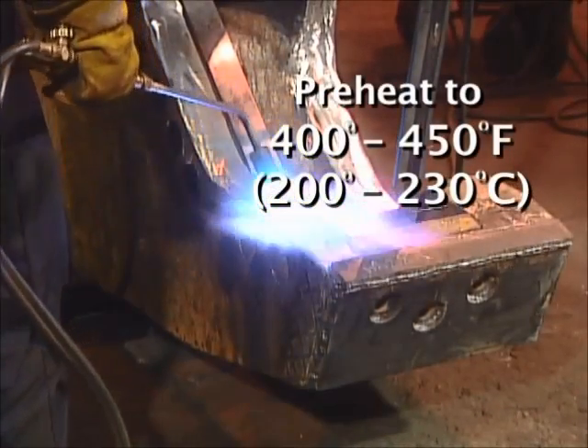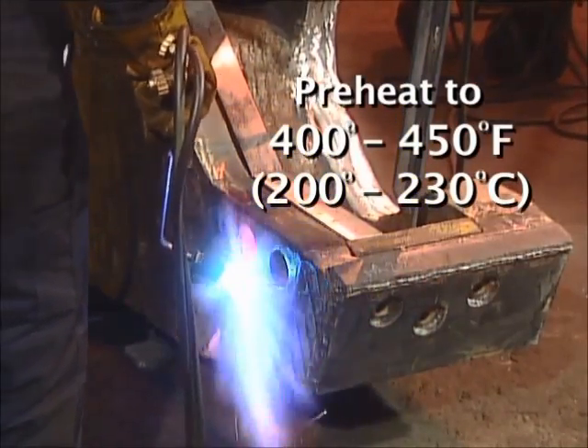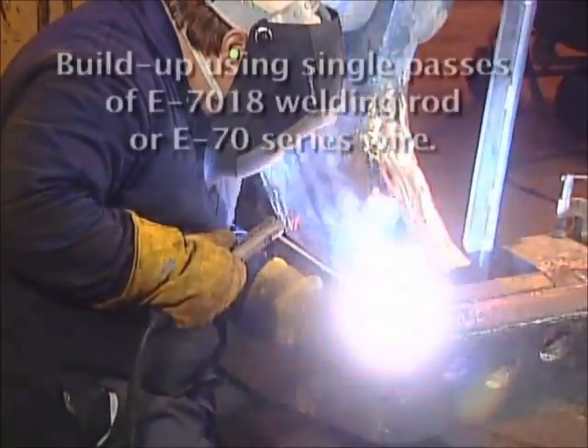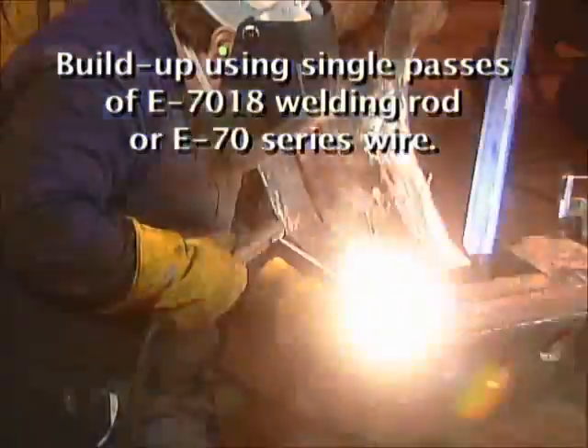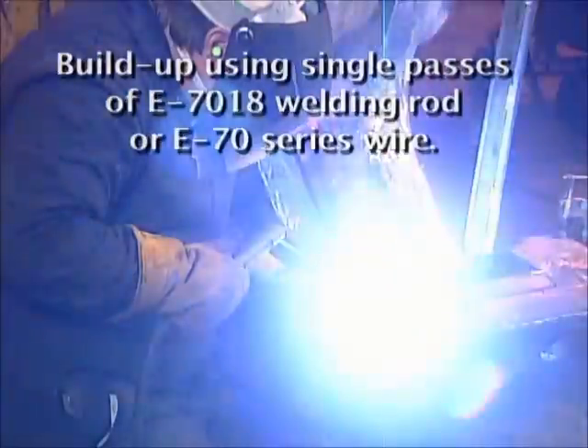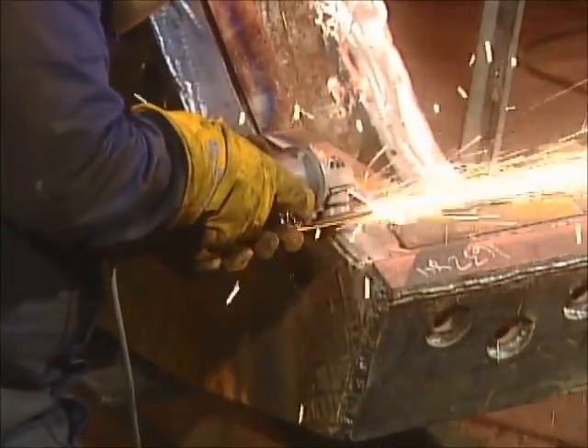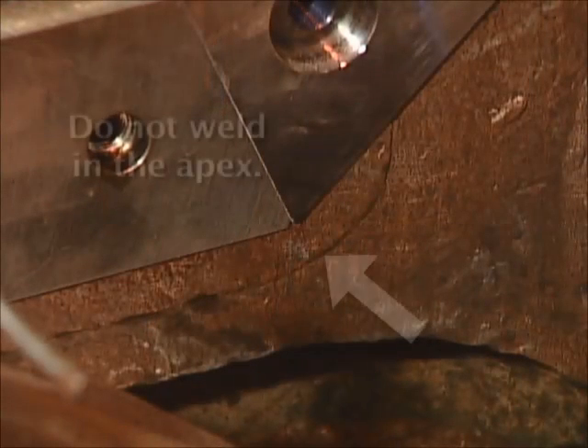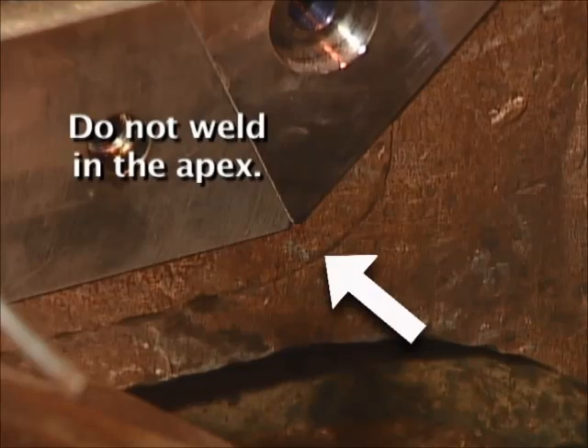When ready for welding, preheat the area and maintain the proper temperature throughout the welding process. With the lower shear grounded, apply buildup to the worn areas in single passes, side by side, running with the grain of the base metal. Peen each pass to relieve weld stress and remove slag. Grind all edges to 90 degrees. If necessary, build up the area beneath the edge of the secondary blade so it is flush with the blade. The blade should not stick out beyond the edge of the blade seat in this area. However, do not weld in the apex area.